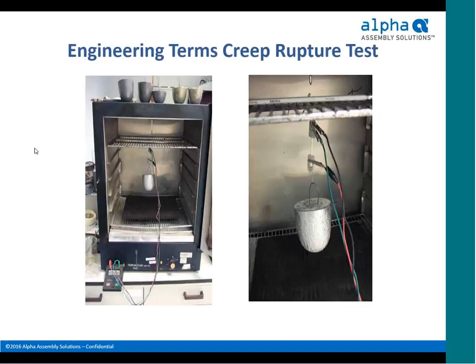Doesn't look very high tech because it really isn't. You take a known mass across a pre-prepared tensile sample like we see here and hang it from the sample and wait for it to fail. And the creep rupture test, it's measured in how many hours to failure. In a creep test, you're measuring stress and strain and physical deformation. So this test is a lot easier to fail because you just walk away from the chamber and come back after it opens up, and you can see how many hours it took to fail.